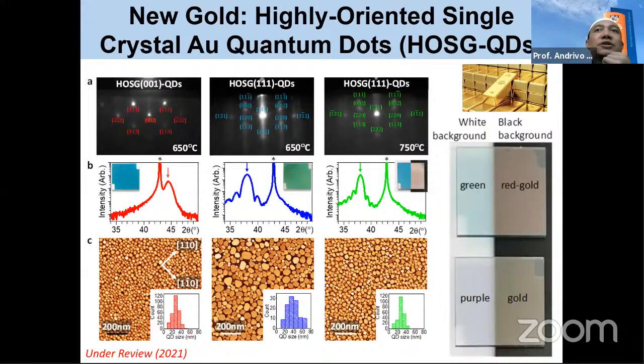And this is what you see here: by doing research using the facility, we have gold, which is a yellowish color. We now make it transparent with different colors. So we can make green transparent, red transparent, purple gold. And you see here, they are very much like what we wished for, and they can fulfill it. This happens because we are able to make the gold oriented with a specific condition.